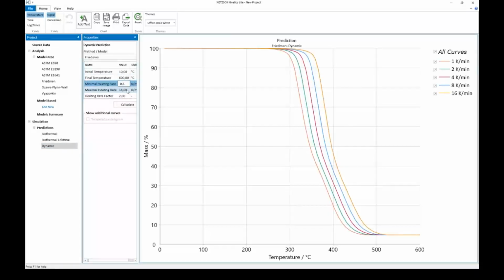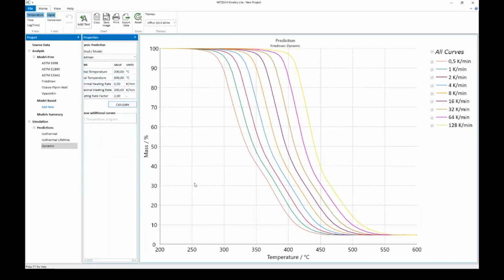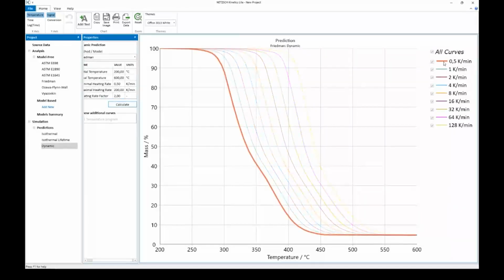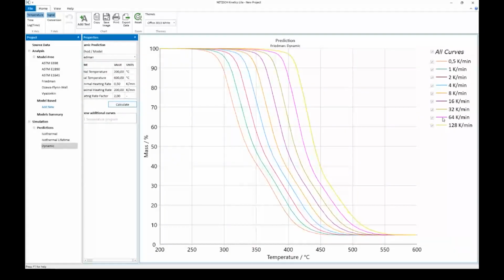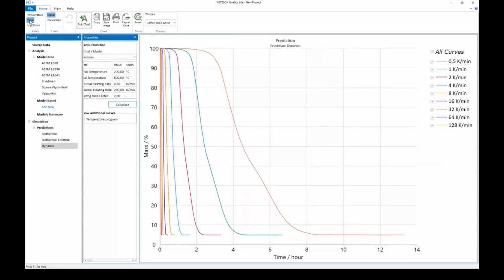per minute, maybe also for up to 128 K per minute with factor 2. So it will be 0.5, 1, 2, 4, 8, 16, and so on, up to 128. And we will start from 200 degrees C, make calculations. Now is our result. We see what happens at 0.5. We see what happens at 64, at 128, and so on. That was dynamic predictions. Isothermal predictions, I will just switch to time.